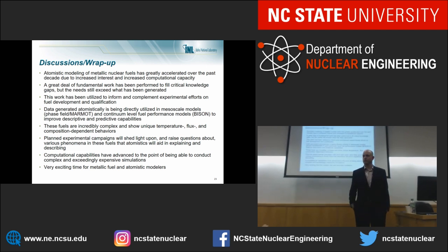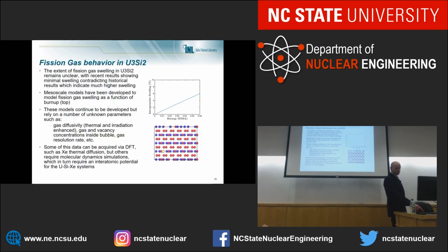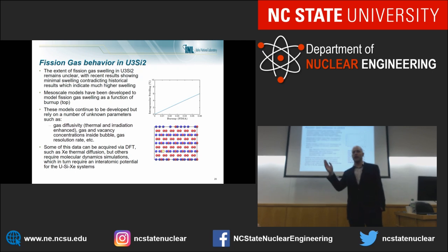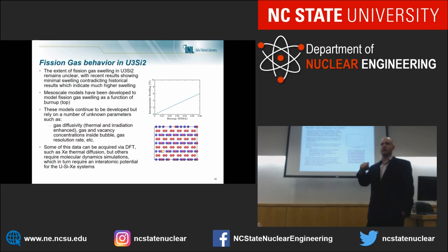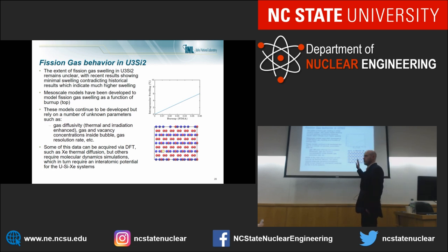Can you show slide 20? Yeah, so that is a xenon atom that I'm looking at. This is just an example of a U3Si2 system where I stuck a xenon on a silicon site in order to analyze a xenon on a silicon site substitutional defect. And there are 3 different sites within the U3Si2 lattice as well. So you can see formation energies, 3 different substitutional energies, and then there's any number of interstitial energies as well in these systems.